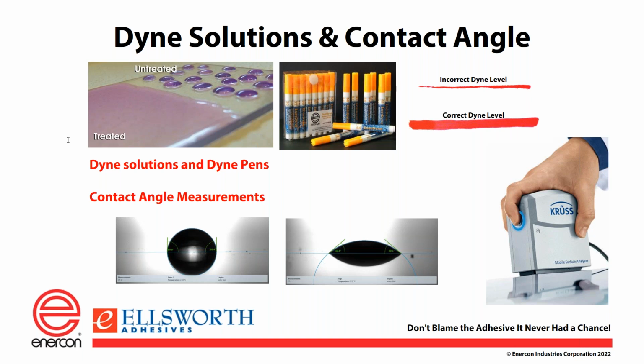You can see what you would do in this case if you were using a dyne pen and you were trying to test, say, at 50, and you would mark a line like you see over there on the right side. If that line collapses on itself really quickly, it is said to have failed that, so the dyne must be lower. But if it marks like the Sharpie type mark underneath the correct dyne level, that means it passed at 50 and your surface is at least at 50. So if you're using this in manufacturing, you may have decided in engineering trials, okay, I need at least 50 dyne to get a good bond, and so you would do that test.